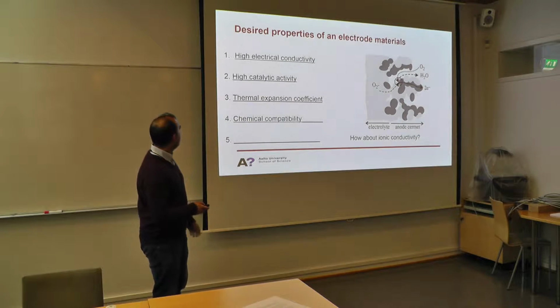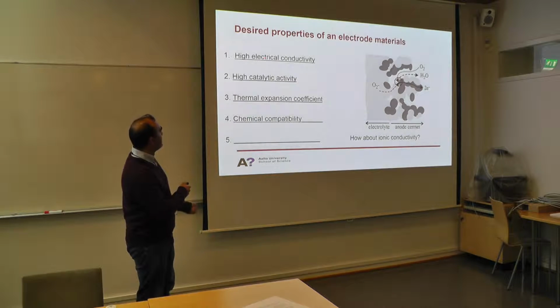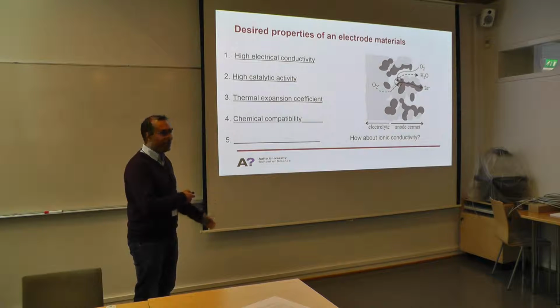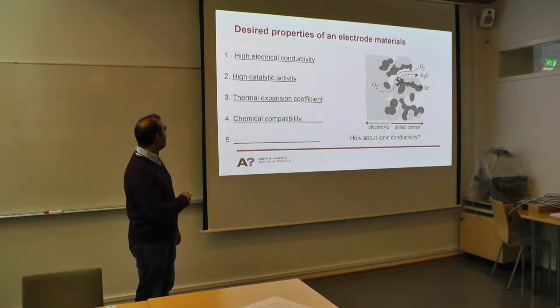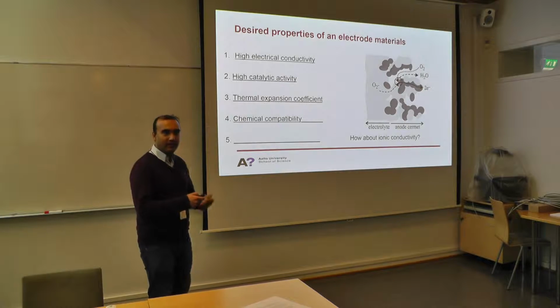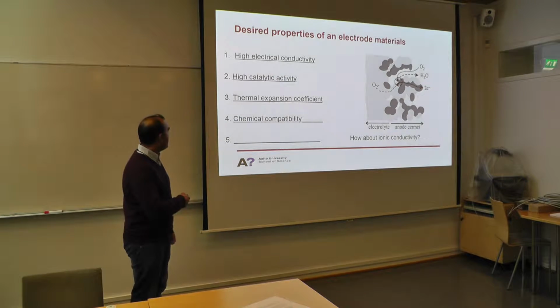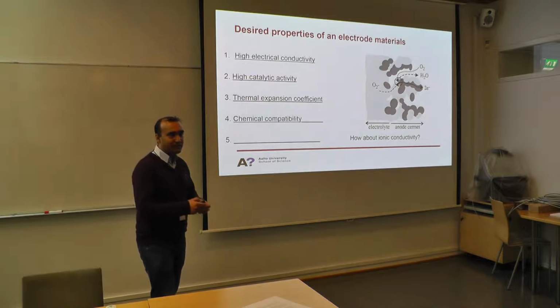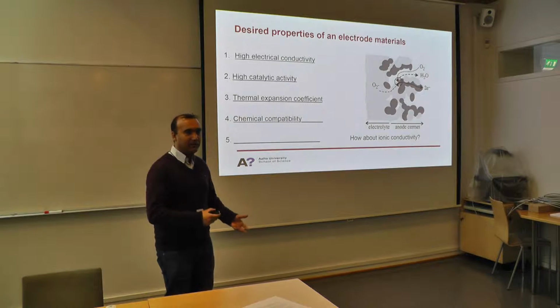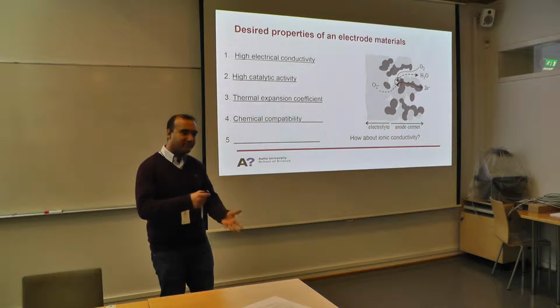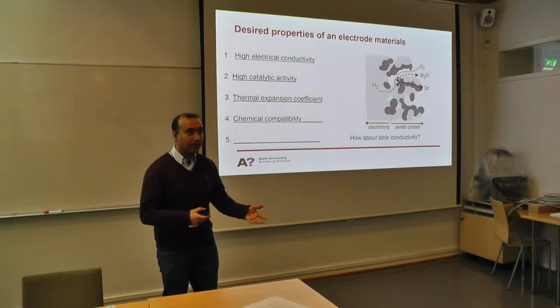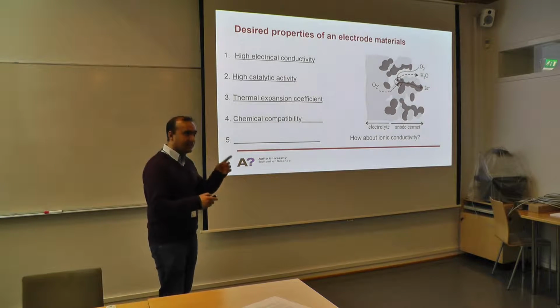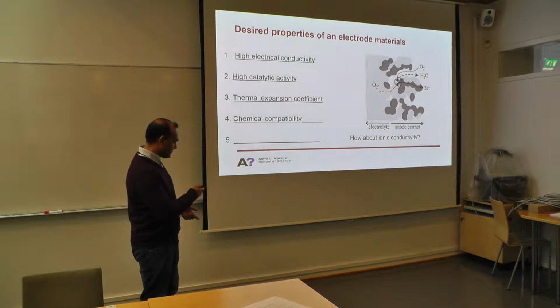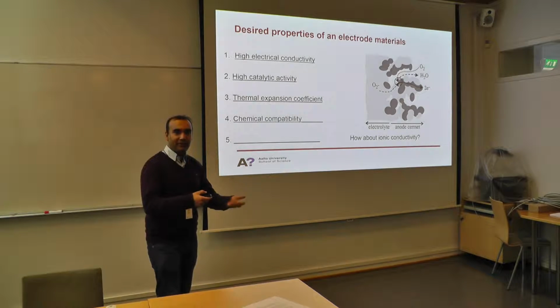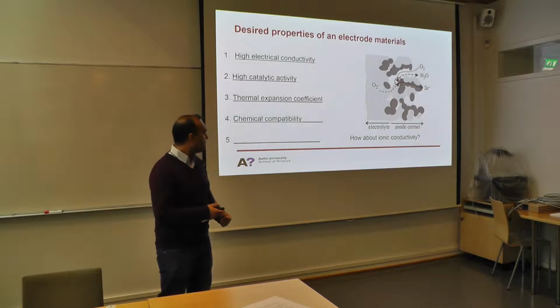Excellent. So basically here I put my own list. They should have good electrical conductivity so that they can conduct electrons. They should have good catalytic properties. They should be good catalysts. And then the thermal expansion coefficient should match with the other materials, because if the thermal expansion coefficient is not matching and we operate the device at high temperature, there is thermal mismatch and it can lead to cracking or this kind of issue. So this is also one issue that we need to take into account. Chemical stability, they should not chemically react with our electrolyte and create problems.